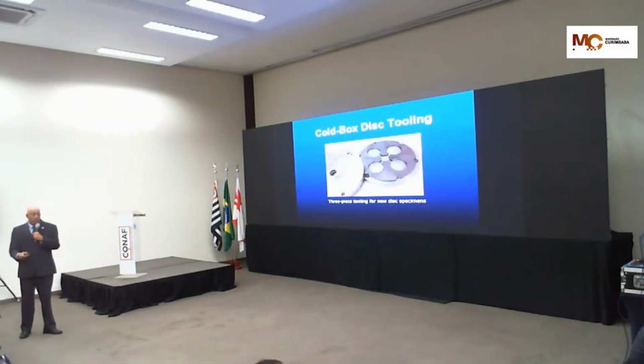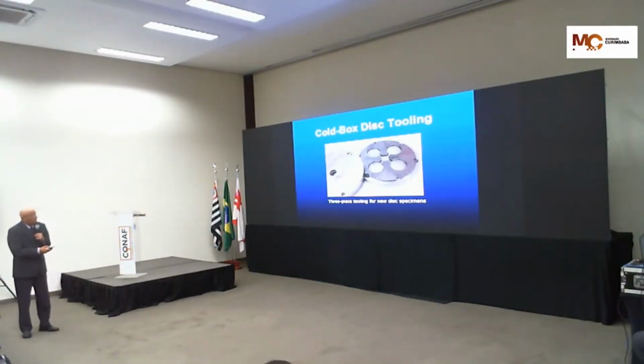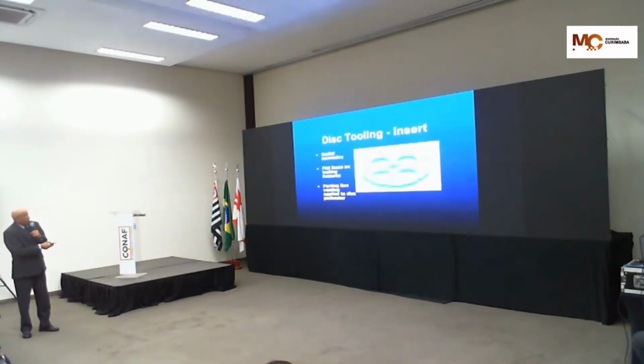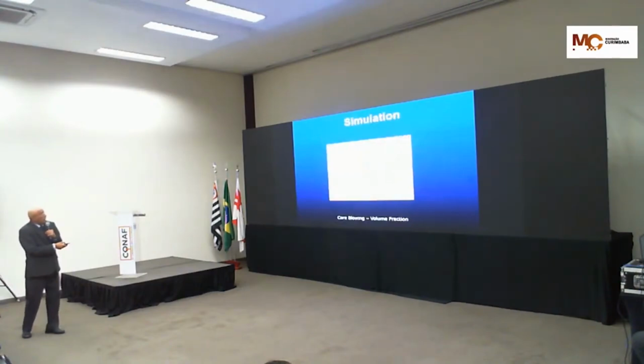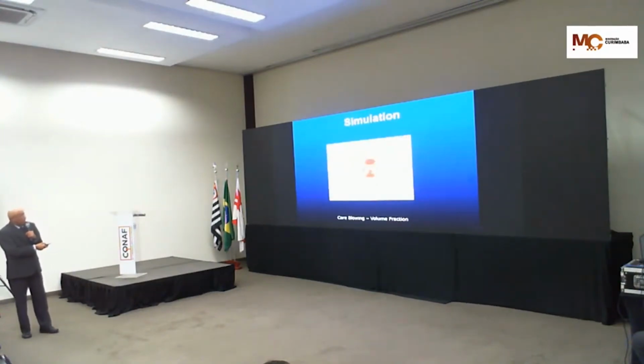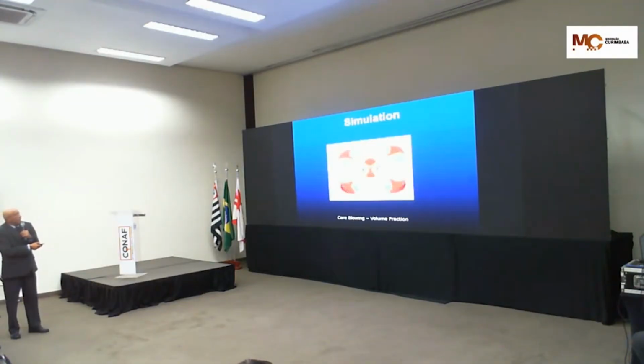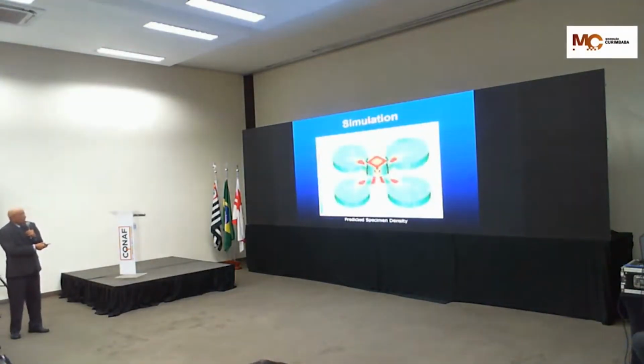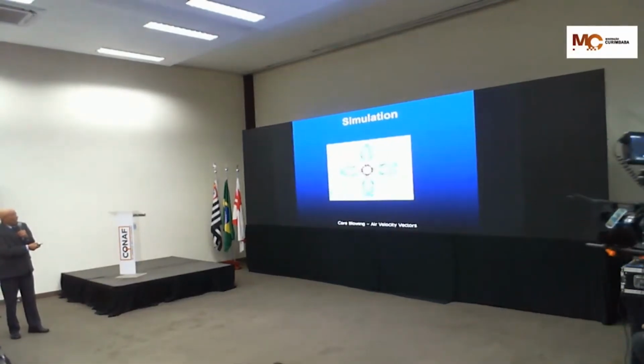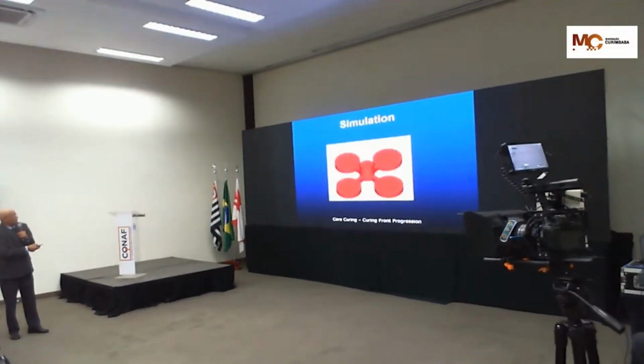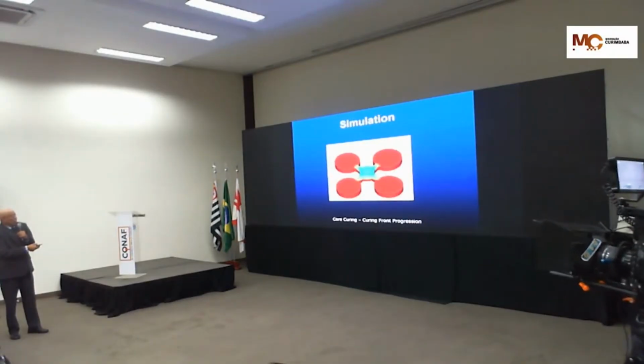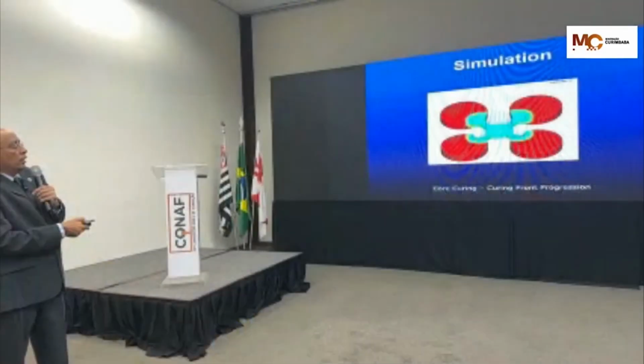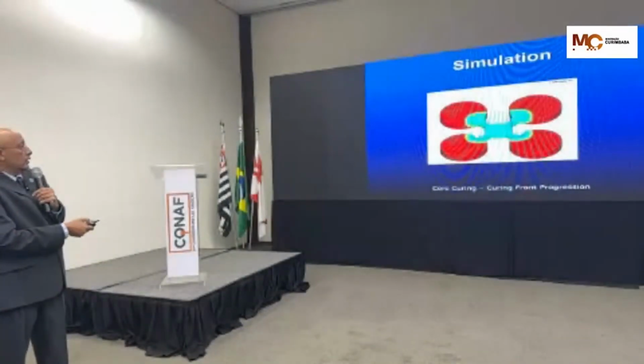Okay. Next process is the cold box process, and this is showing you some tooling. This is a 3-piece tooling, but it can be more. To give you some ideas, we have to vent this tool around the parting line, and then some simulation for blowing the cold box system. We can predict the density from simulation and look at the blow pressures through gassing those cores, and then the curing and curing front progressions as we purge the catalyzing gases through this system.